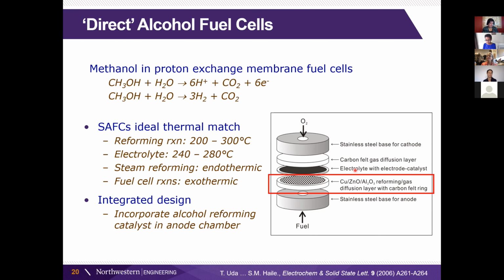In this case, we have our electrolyte, and we've got the electrocatalyst on either side, but on the fuel side we introduce an additional what's called a reforming layer. So this is a common catalyst for converting methanol into CO2 and hydrogen, and that hydrogen then becomes available for our fuel cell. And what's nice about this entire system is that the fuel cell is exothermic because we have these resistance losses, whereas this reforming reaction is endothermic. So we can match these such that the thermal balance is good, and then we don't have to insulate quite so significantly to manage the thermal management of the system overall.